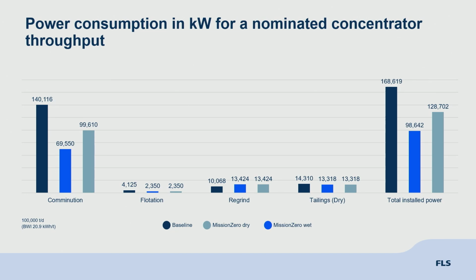With dry classification, you have big fans and you have air-swept material that go through it. And when you're trying to produce a 250 or a 350 grind, you have to use a lot of air to move that material. And that costs you a lot of money in energy. So, as you can see by the results, if you're using coarse flotation, and not all materials are amenable to coarse flotation, then the wet grinding circuit comes out on top.